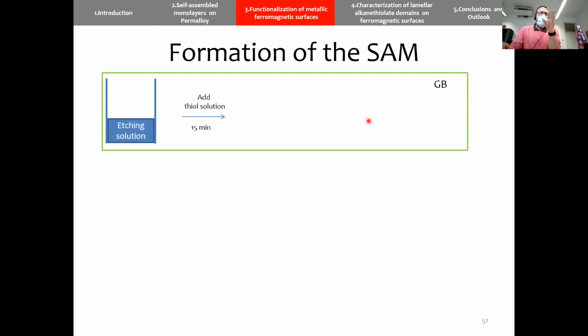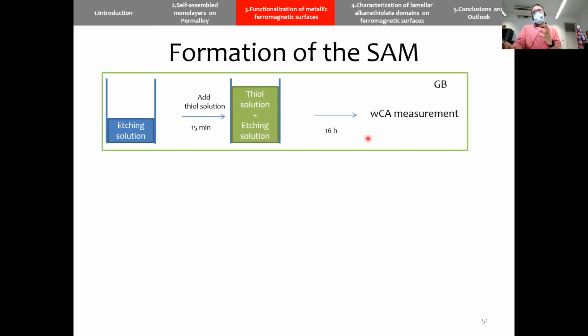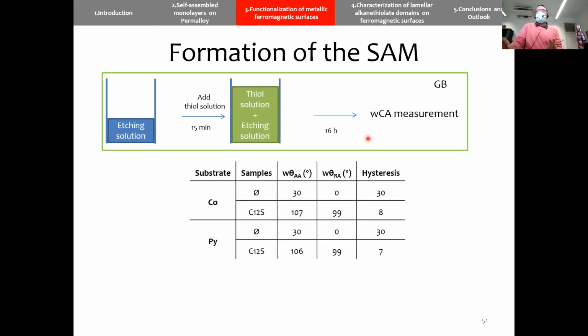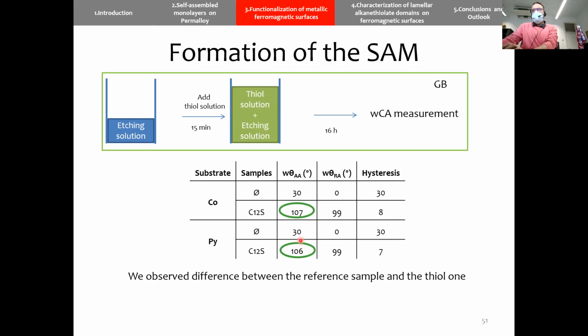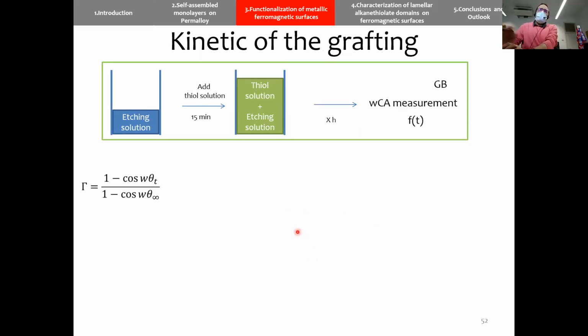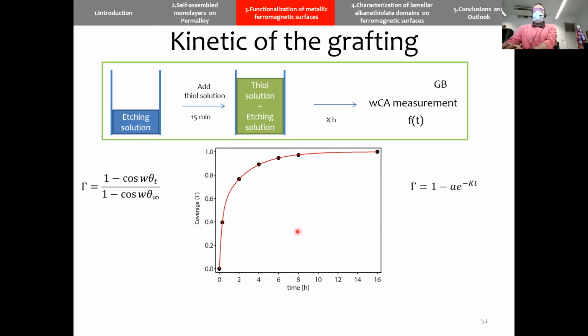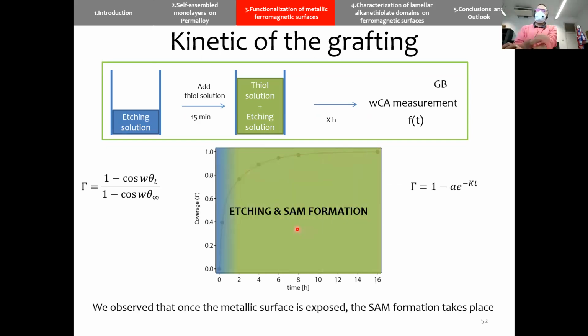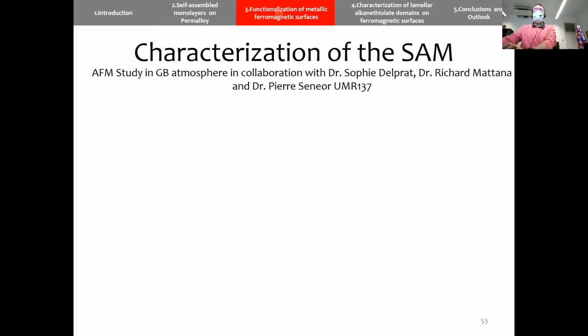We started with this. So we prepared the solution, and after 50 minutes, on top of the same solution, we added the thiol solution. And we measured the contact angle, and we observe that there is a difference. So we have a SAM with respect to the reference. Also, we did a study in time, and we see that once the etching is finished, the SAM formation takes place. So first the approach and then the stabilization.